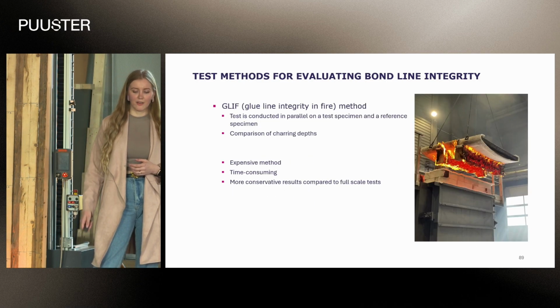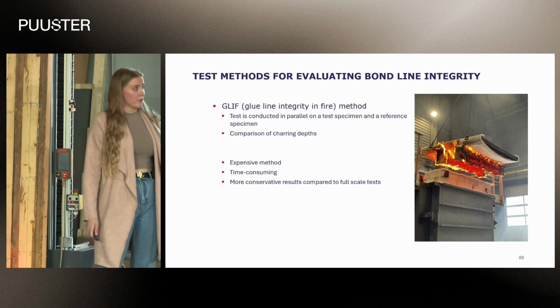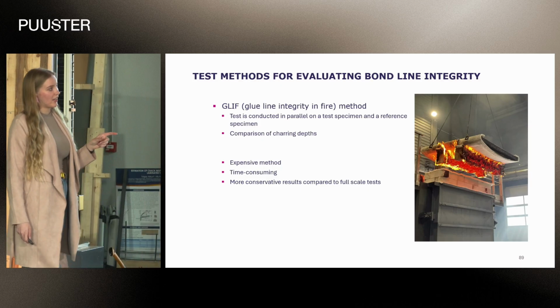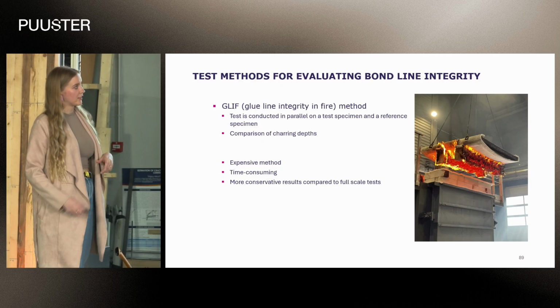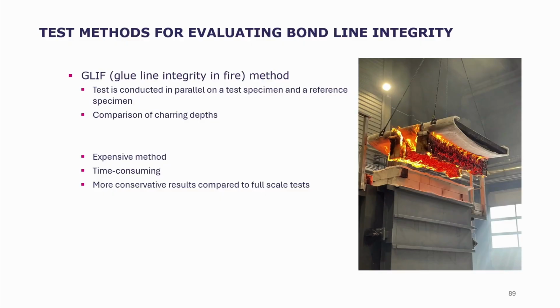So in Europe, we have stepped down a little bit, and we have implemented the GLIF method, which is a model scale method, where we burn 2 specimens, a test specimen, a reference specimen, at the same time in a model scale furnace. And after the test, we just compared the charring depths, and depending on the difference between the reference specimen and the test specimen, we can divide the adhesives.